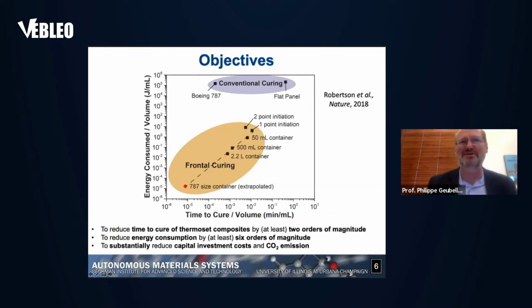Obviously, we haven't made a 787 at this point, but the objective is really to reduce the time to cure by about 2 orders of magnitude. So go from hours to minutes, and reduce the energy consumption by many orders of magnitude, whether it's 3, 4, 5, 6, or even more. That would make a major difference. And in doing so, we would substantially reduce the capital investment because we want to make this out of an autoclave, and reduce the CO2 emission as well.